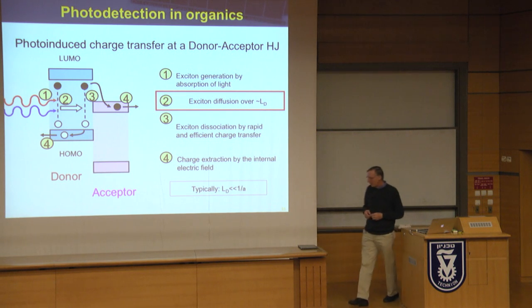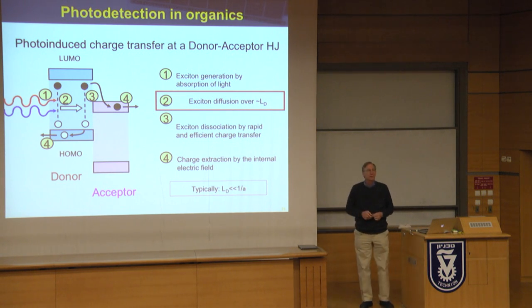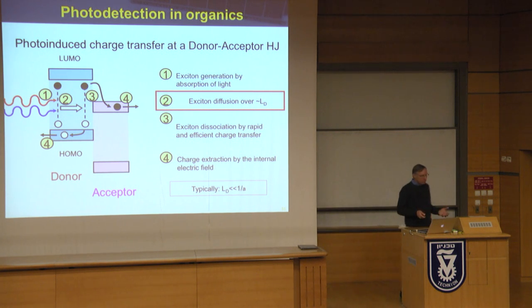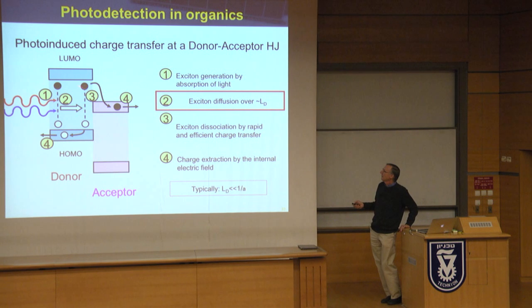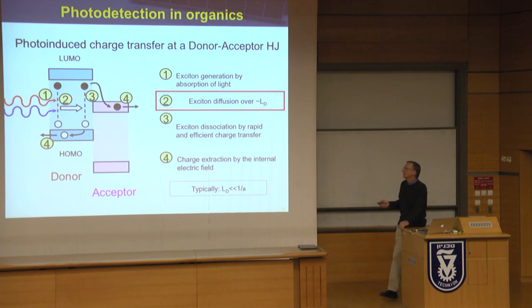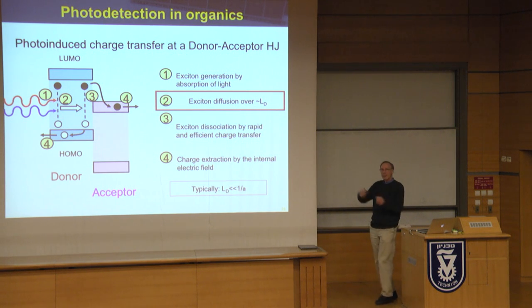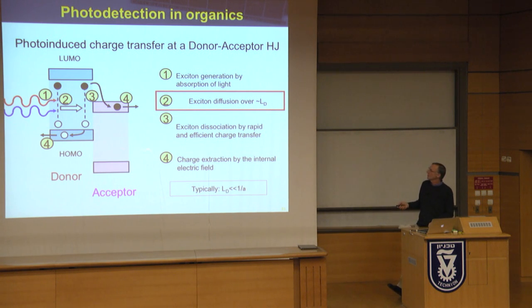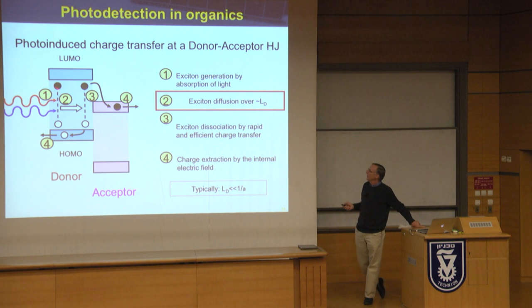But organics provide us with a significant challenge in that we don't generate free charge by the absorption of a photon. What we do is we come in with a photon and we create a molecular excited state called an exciton that has to drift toward a junction, and that electron then sees the conduction level of what's called the acceptor molecule. So there's a junction between a donor layer and an acceptor layer, and it sees that its energy is more favorable on this side, and it creates what's called a bound charge-transfer state, where the electron and hole are bound across that interface, but eventually they work themselves loose and you get charge out. And this is a pretty complicated process.